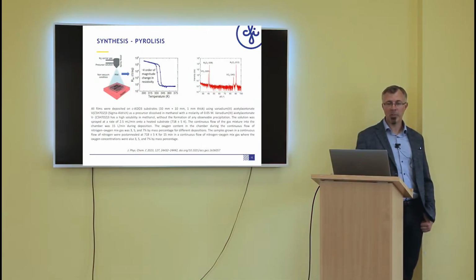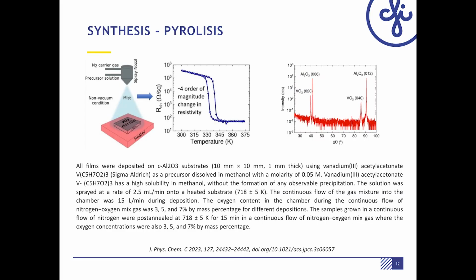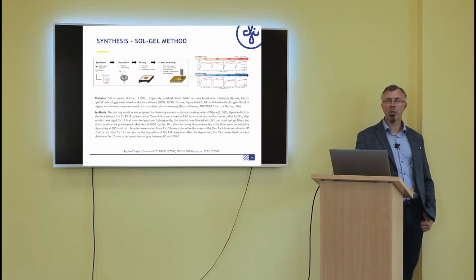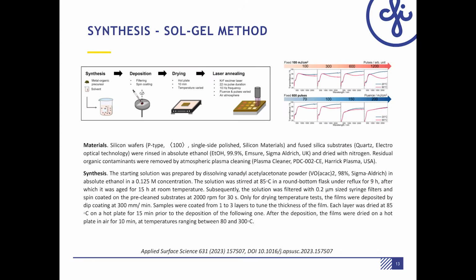The next method is pyrolysis. After preparation of a liquid precursor solution, it is spray coated onto a hot substrate. It is possible to achieve very good physical properties of vanadium dioxide thin films. Quite a close method is the sol-gel method. So first of all, a solution is prepared from vanadium dioxide precursors. It is aged for a certain time at a certain temperature, and after that the sample is coated with the vanadium dioxide precursor and dried.